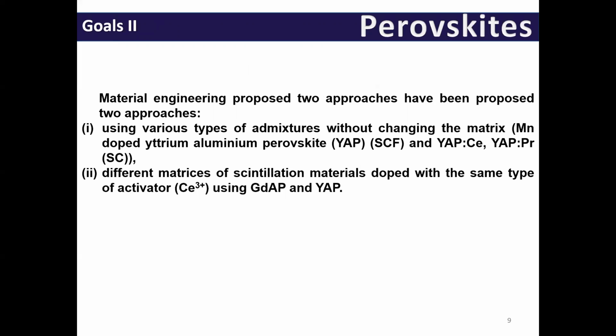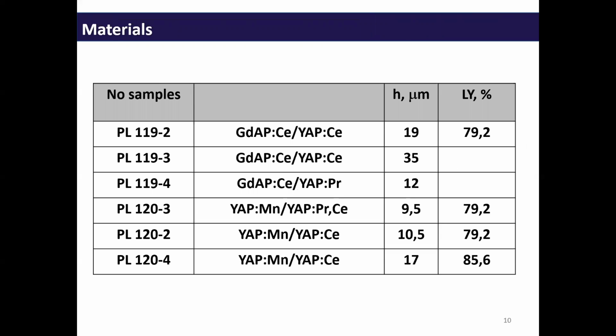The second part of my presentation is about perovskite. Two approaches to material engineering have been proposed: using various types of admixtures without changing the matrix, and using different matrices of scintillator materials with the same type of activators. The mentioned material hosts possess different densities and effective atomic numbers, heavy gadolinium-based garnet and much lighter yttrium-based perovskites, and for this reason can be applied for the simultaneous registration of alpha and beta particles, as well as X-ray and gamma quanta in wide energy ranges.